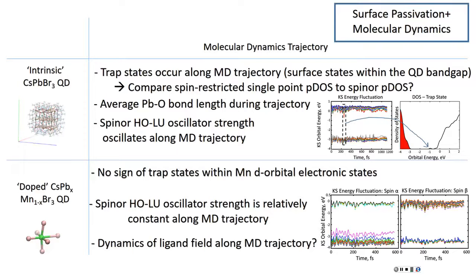That would definitely be handy. Because you can decompose it on each type of atoms or type of bonds, you will clearly see this connection, going to a question from Dmitry: does this oscillation, which you already see in the electronic levels, really relate to the normal modes? Or let's say, is it correlated with a frequency typical for lead, or lead bromine, or maybe even cesium lead, even if they're not really creating a bond, but they do some kind of motion which might be involved in the vibrational mode?